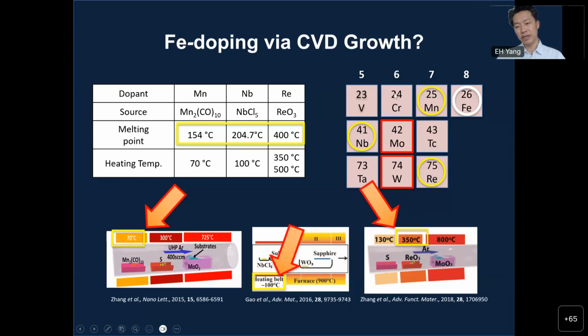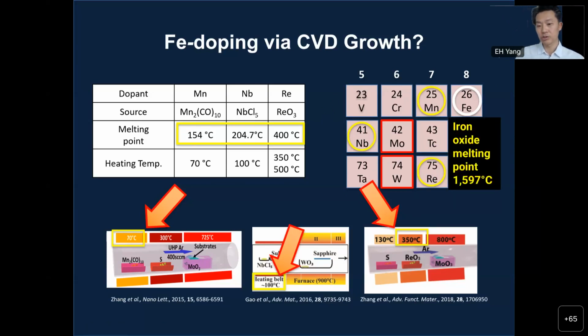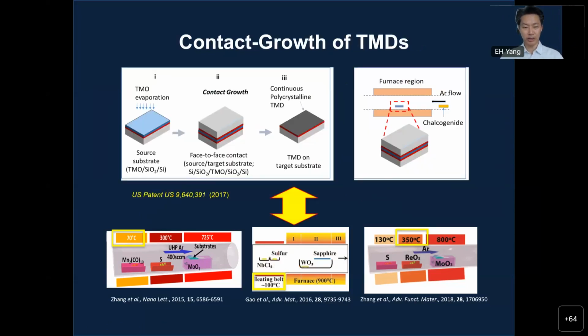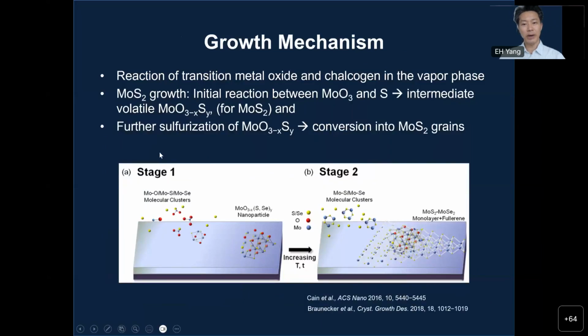In the case of iron, one has to use iron oxide, whose melting point is close to 1600 degrees C. So how to solve this problem? You have to use a different process here. Instead of using powders outside the heating zone, we use evaporated thin films, thereby providing better uniformity in the process, or sublimation or gas flow in this local region, and then put the iron oxide materials there. So the basic mechanism is as follows.